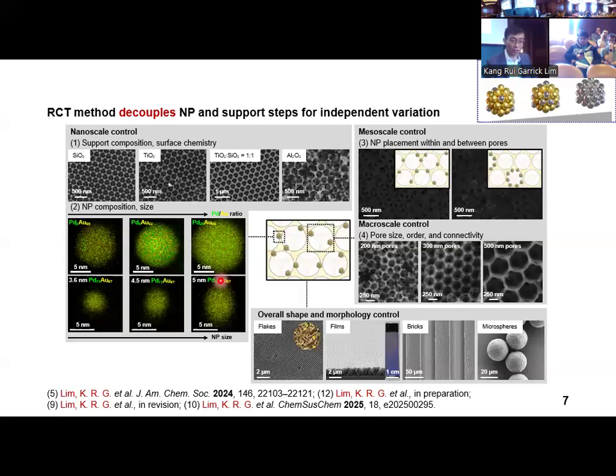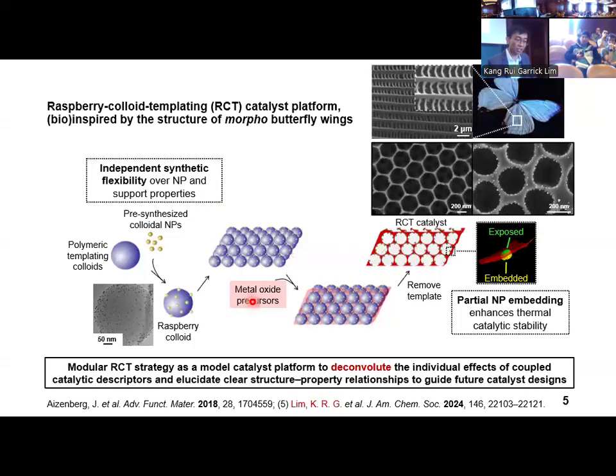And if I can elaborate just a little further, the choice of the support does not need to be that of a solution phase precursor. So in this step, you can use preformed metal oxide nanocrystals of perhaps titania, ceria, of well-defined facets, and you'll be able to jam them to form the entire support structure. And that gives you another lever to direct reaction performance, not just by using the nanoparticles to your advantage, which is what most people typically do, but also by using the support chemistry and nanoscale properties of the support, which is not quite possible with traditional methods, where you would form the support on a macroscopic, micron scale. So I think that's what distinguishes our method from what is currently available and what's currently used industrially.